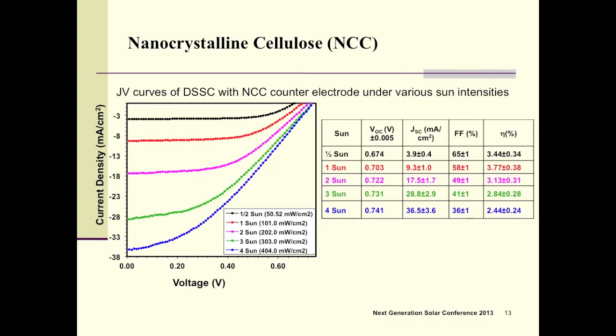So we use these in our dye-sensitized solar cells, and these are the JV curves under different sun intensities. At one sun, we got 3.77% efficiency, which is quite encouraging. These are our initial results. But you can see that at higher potential values, we are getting higher series resistance that is killing the efficiency of our device. So currently, I am working to optimize this device so that we can get much more from this system.